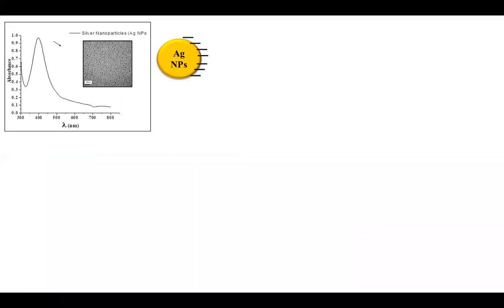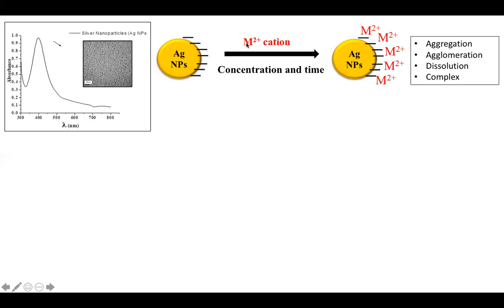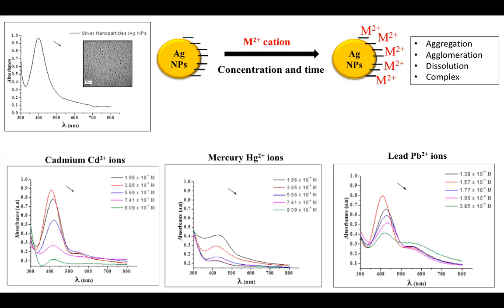As we look at silver nanoparticles in this study as a whole, we were able to see that our synthesized nanoparticles were stable initially, with that ideal, uniform peak that shows the nanoparticles were monodispersed and easy to see with the citrate coating on the outside. As we added our cations with 2+ charges, we looked at the change in concentration over time to see if any changes occurred from aggregation, agglomeration, dissolution, or complexation. In comparison of cadmium, mercury, and lead, each of them showed a different reflection of how they behaved in the presence of silver. As a way to see the changes over time, we compared to our control of silver alone.